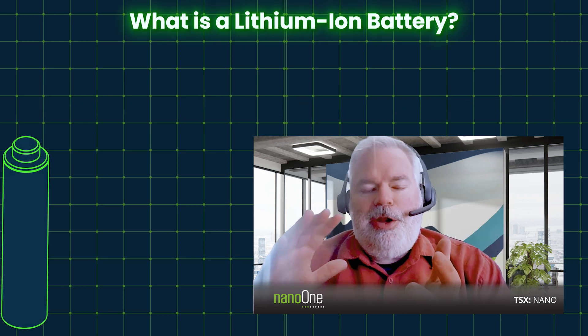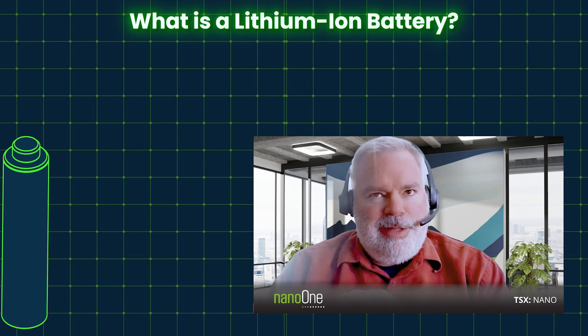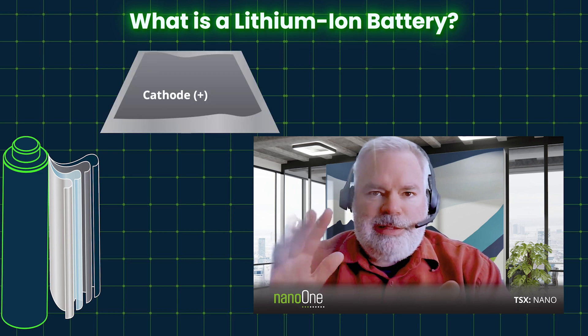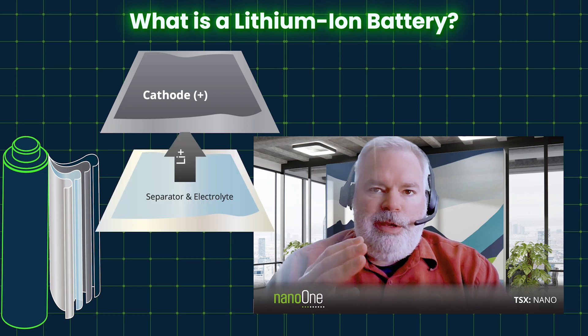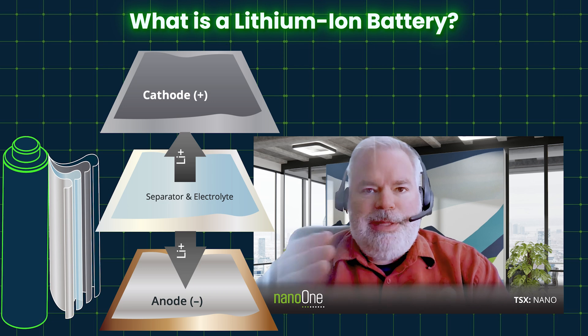What is a lithium-ion battery? A lot of components put together. I like to say it's kind of alchemy making batteries — it's a very complicated thing. In fact, it's really a lot of films that are rolled together, incorporating first an aluminum foil on which we would put a cathode material, a powder that's impregnated on it. Then there would be a separator, then a copper film on which we would put a graphite material that would be the anode.